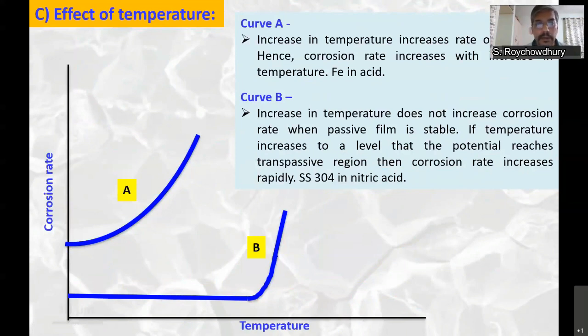Another possible behavior is like this curve B. In curve B, what happens is with increase in temperature, the corrosion rate does not increase, but beyond a certain temperature, it increases rapidly. Again, if you remember, I told you that the oxidizing potential, the nature of the environment, also depends upon temperature. So increasing temperature means the oxidizing potential is increasing. If you have a stable passive film, there is no increase in corrosion rate. But if temperature increases such that the transpassive region is reached, then this passive film will degrade and transpassive dissolution will start. So two kinds of behavior you can see, behavior A and behavior B.